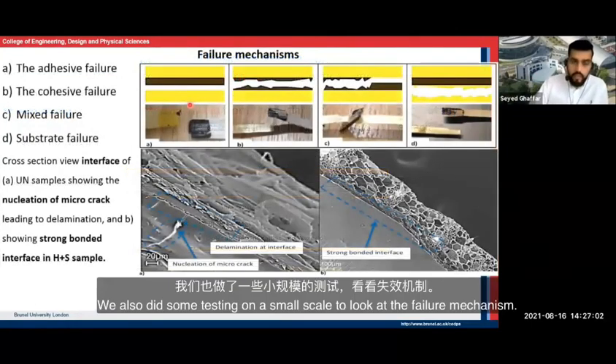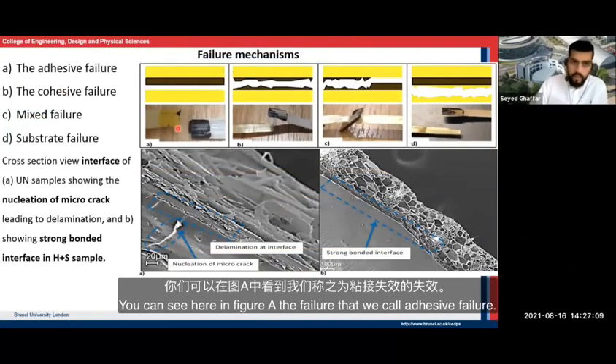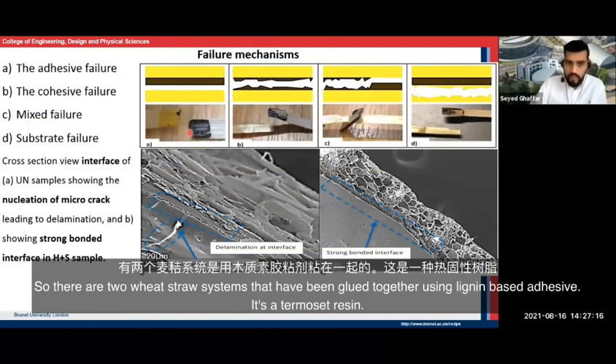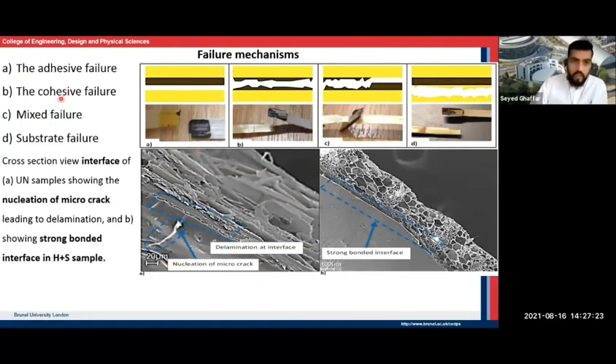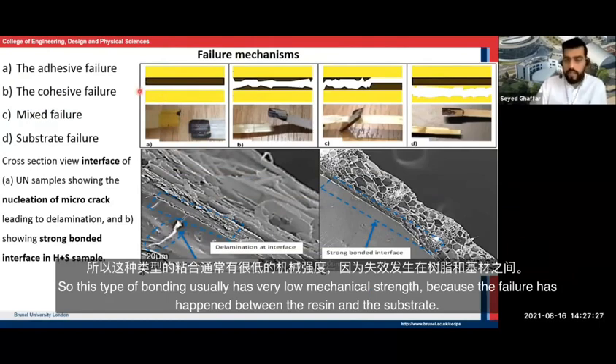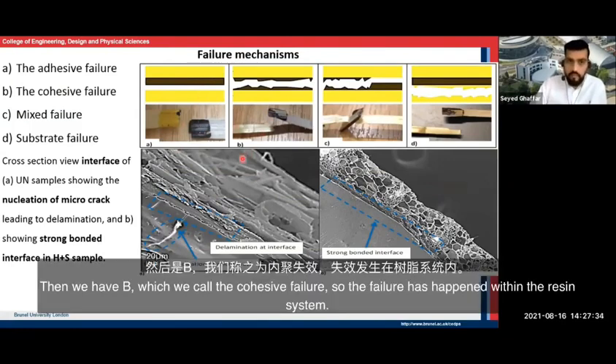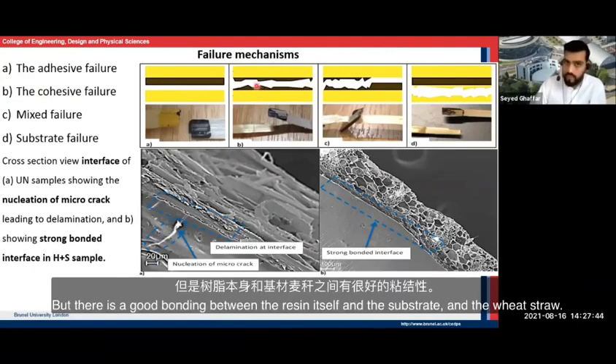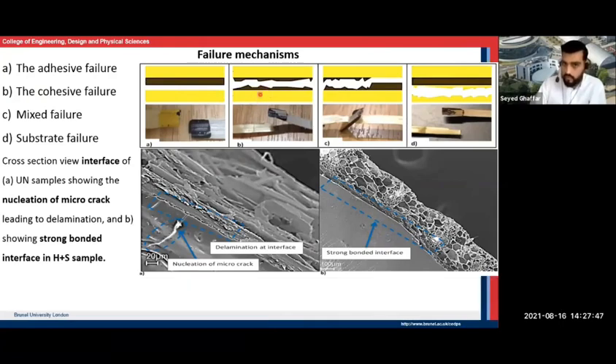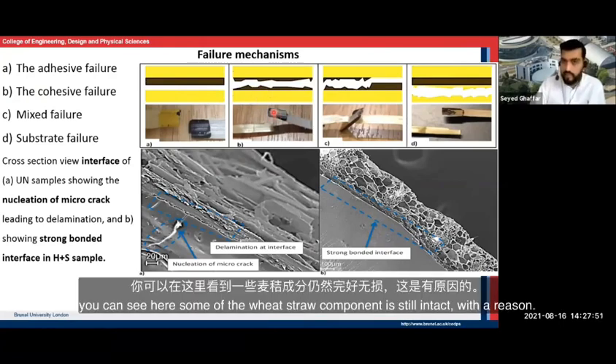We also did some testing on a small scale to look at the failure mechanism. You can see here in figure A, the failure that we call adhesive failure. So there are two wheat straw systems that have been glued together using lignin-based adhesive, which is a thermoset resin. This type of bonding usually has very low mechanical strength because the failure has happened between the resin and the substrate. Then we have B, which we call the cohesive failure. So the failure has happened within the resin system. But there is a good bonding between the resin itself and the substrate and the wheat straw. You can see here some of the wheat straw component is still intact with the resin.